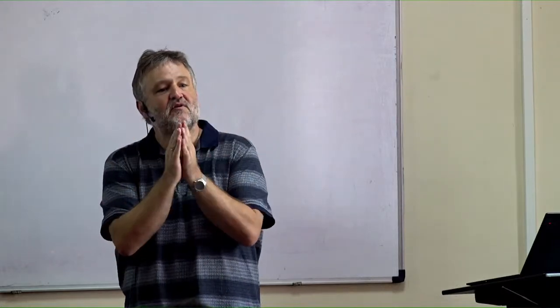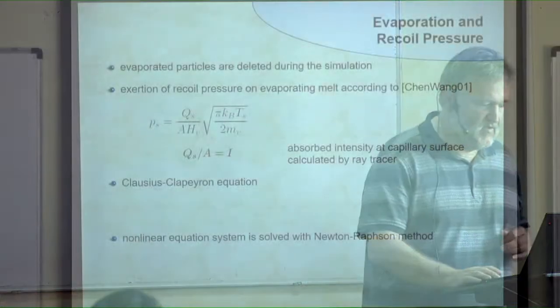So now if you do deep penetration laser welding, the situation gets even worse. For example, if there is this capillary where the material is vaporizing and leaving the simulation, and the liquid is coming from outside, then it would immediately fill the capillary. And then the capillary is gone. So there's therefore a recoil pressure. There's a pressure pressing the liquid out of the capillary, and you have to compute this.